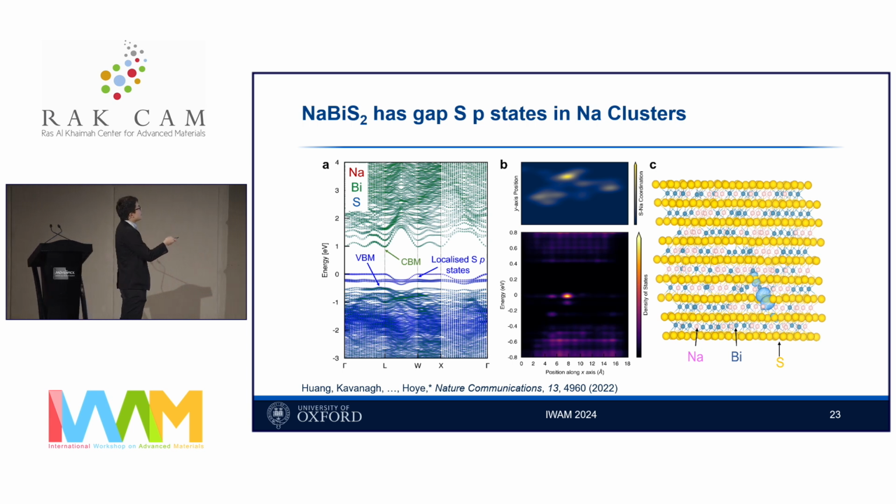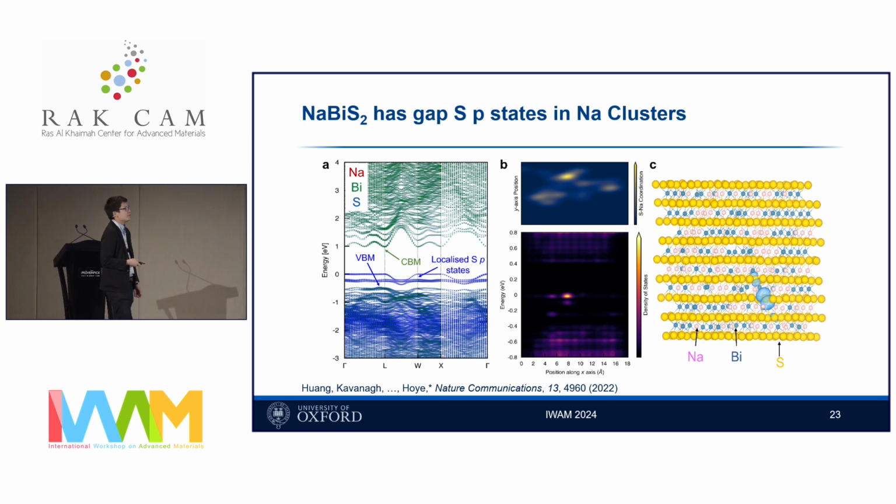And here, this is a plot of the density of states, a map of the density of states in real space, so y-axis versus x-axis, you can see that there's a high cluster over here. And this cluster over here occurs when there's strong coordination of sodiums around the sulfur. Because, as I mentioned earlier, the sodium and the bismuth, they occupy the same lattice site. But when we grow these nanocrystals kinetically, they aren't necessarily organized in a uniform and homogeneous manner. So we get clusters of sodiums and clusters of bismuth.